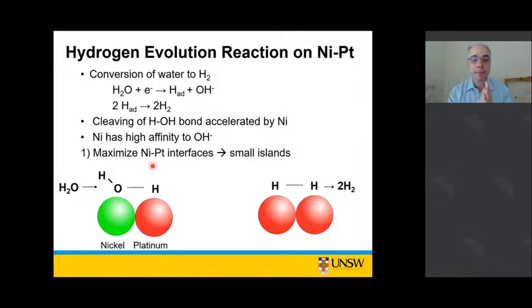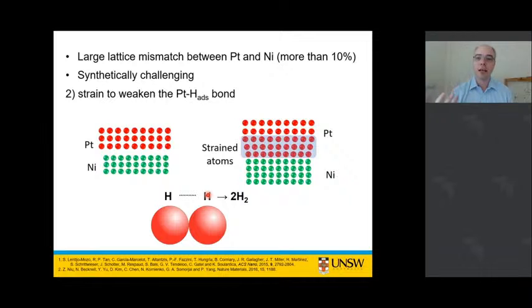So if we want to think about catalyst design, to make good catalysts, what we want to think about is, first of all, maximizing the number of our platinum nickel interfaces on our catalyst. So we want to have a lot of these platinum nickel interfaces to make a good catalyst. That means we want small islands where there's a lot of those interfaces around the islands. And then the next trick that we can do is think about introducing some strain into the system. A lot of people have been thinking about how you can use strain to improve the catalytic properties of nanoparticles.